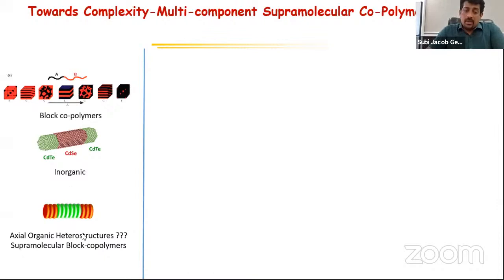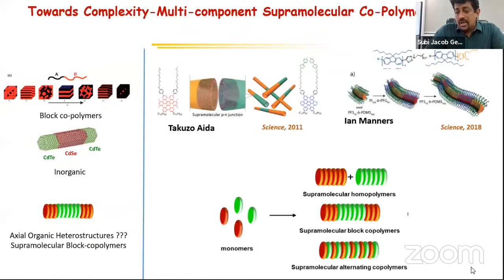And one of the special structures we are interested in is axial organic heterojunctions, because we are people working on organic pi-conjugated systems. If we can create something like one-dimensional stacks with P and N type, or different semiconducting molecules, we can get a very nice exciton migration along the stacks, and we can do the same tricks inorganic chemists have been successful with in terms of photocatalysis. And we believe that supramolecular polymerization, sequence control, is the only way to make these kind of structures. So this is something which we call axial organic heterostructures, or in principle, if you look into it, it is a supramolecular block polymer, right? It has segmented organization of these monomers. So this is something which we have been doing. And again, we are successful in this particular case.